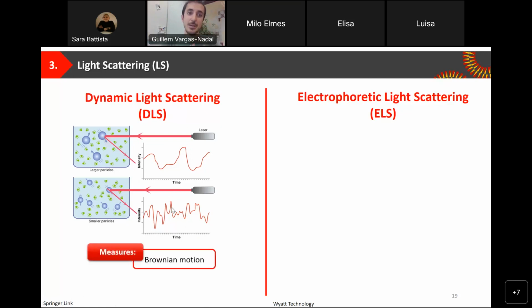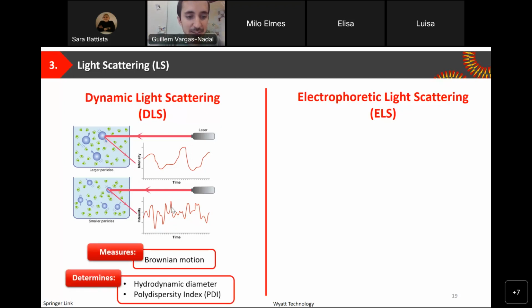So the dynamic light scattering measures the Brownian motion, because with the fluctuations you can know the Brownian motion. However, remember that what the equipment measures is the Brownian motion. And with this, we can determine the hydrodynamic diameter. This is important because this is not the real or geometric diameter. It is the hydrodynamic diameter, which also relates to the molecules that surround the nanoparticles. And it also determines the polydispersity index, which gives information about the homogeneity of our sample.